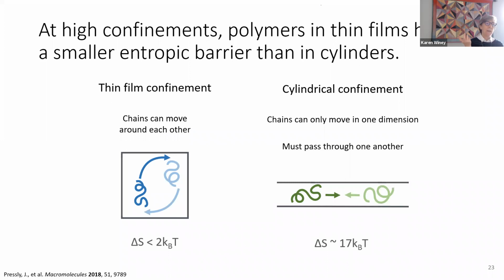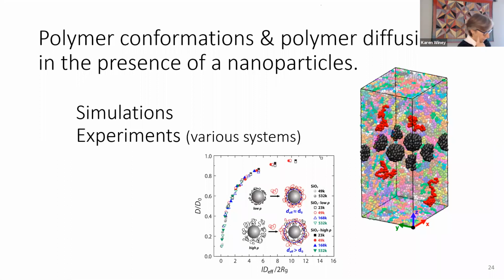And that doesn't happen in the thin films. Even if you're very, very confined in thin films, we see a little bit of tending towards segregation, but still the entropic penalty isn't the same because they can kind of do-si-do around one another. Whereas in the cylinder, the entropic barrier is much higher for the polymers to have to pass one another. So that's what we learned by looking at rigid wall confinement in thin films or in cylinders.